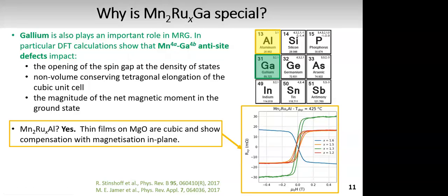Now, you can see there's no massive increase in coercivity, but this is because the films are crystallized basically in a cubic structure. There's very little tetragonal distortion. So the films are fully in plane. There's no perpendicular anisotropy. However, they do show high spin polarization.